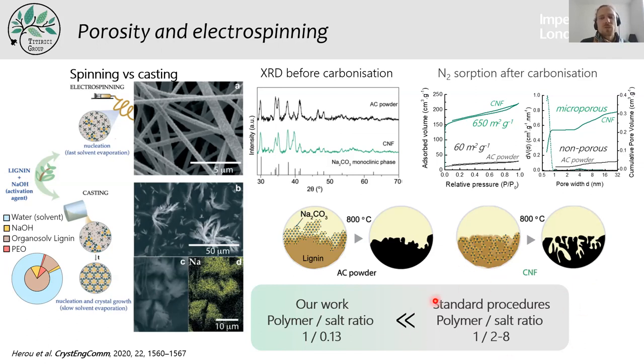And compared to the standard procedure where people do chemical activation, you probably heard about this, they usually use a salt to polymer ratio that is much higher than the polymer content, so 2 to 8. But in our case, because we use electrospinning and this fast solvent evaporation, we're able to use 10% of the polymer weight. And that, of course, is a great advantage in terms of cost and also scalability.